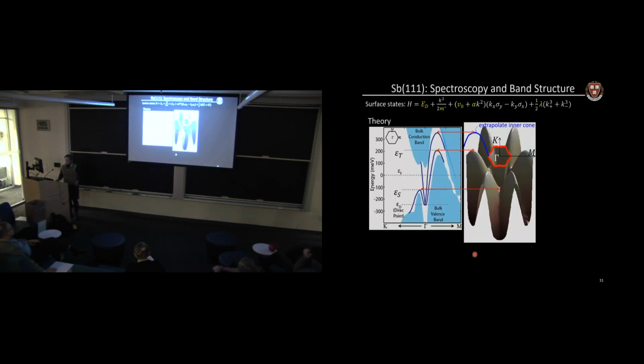And if we look at the band structure, it's a topological material, so we expect it to fit this phenomenological Hamiltonian here. If one does a DFT calculation of the band structure, this is roughly what it looks like. So one expects the conduction band here and the valence band down here. It's actually a semi-metal, not an insulator. So the Fermi level here does cross through the bulk band, so it is metallic. But if you look as a function of momentum, there's a gap everywhere. So it can still be topological. It can still have an inversion between the valence and the conduction bands.